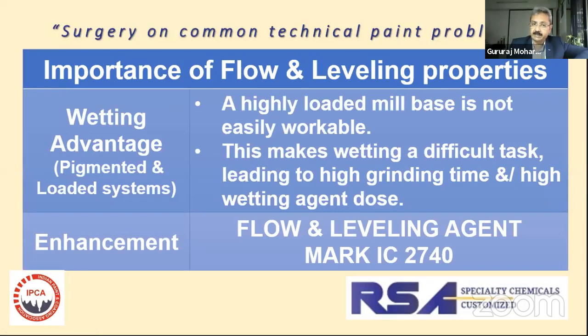Wetting advantage. We spoke about high mill load base with an extender wetting agent. Yes, extender wetting agents do their job, but that job can be made easier if you are using a flow leveling agent. What happens is with a nominal addition of a flow leveling agent in your mill base, the base becomes very easily workable, and the grinding happens pretty fast and efficiently. So the wetting agent dosage required also comes down. Basically, addition of this will optimize the dose of your wetting agent. It will also bring down your grinding time. So it is a win-win situation.